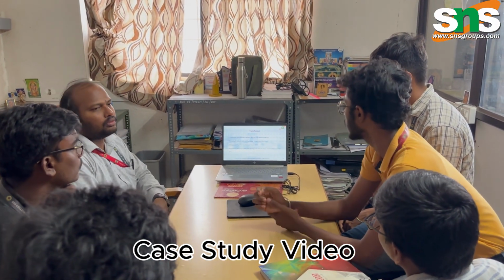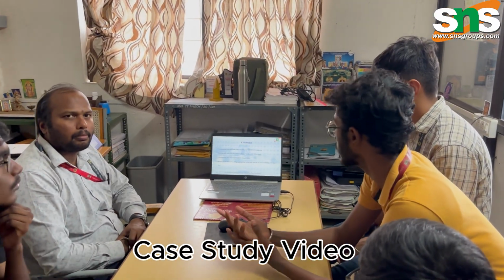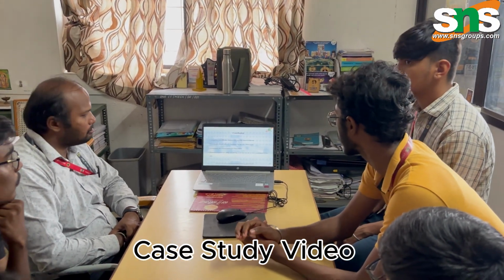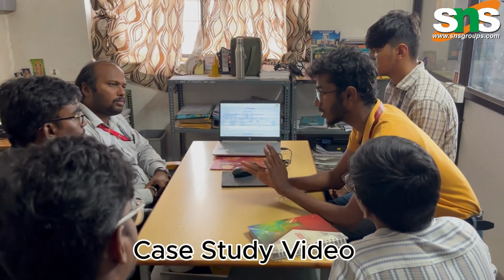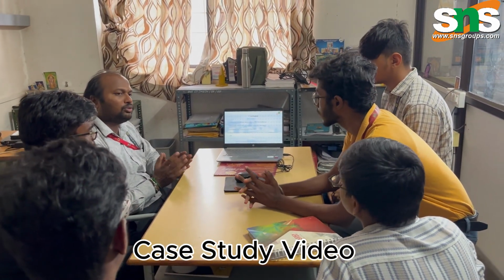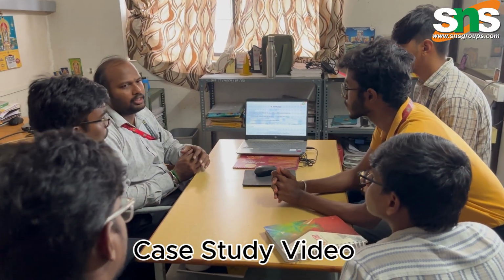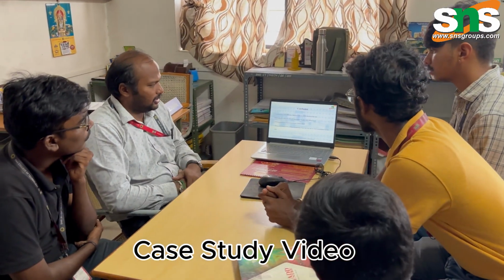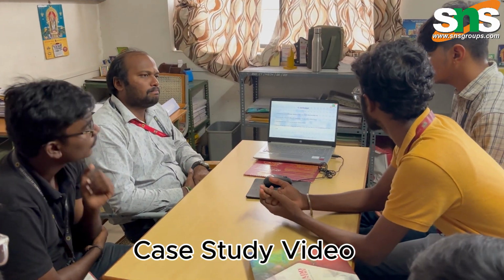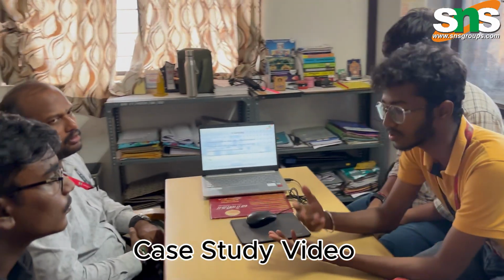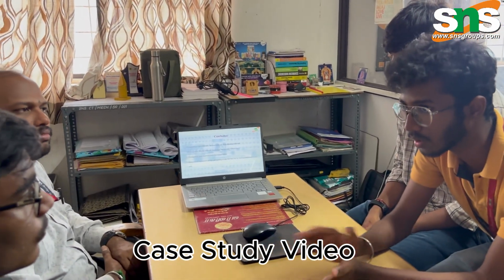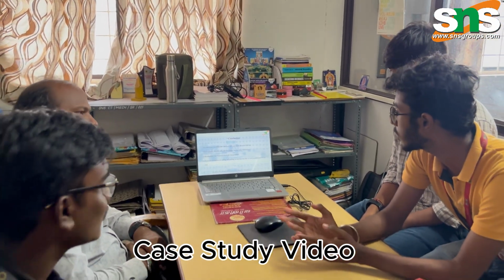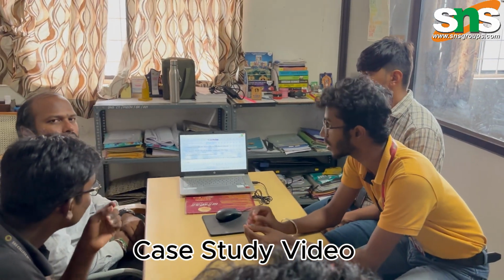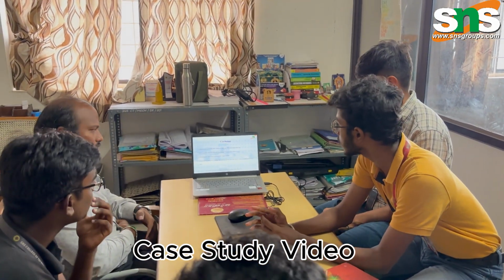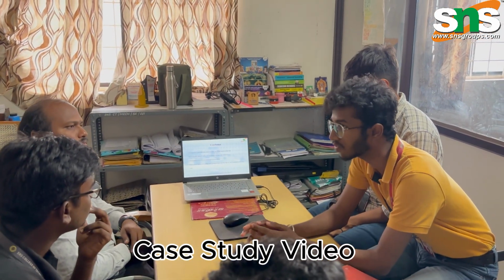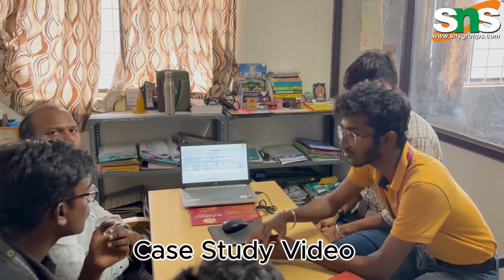Now coming to the conclusion. The composition, the microstructure and the hardness of the gear are satisfactory and at the normal level. The pre-processes, meaning the heat treatment and other machining processes, were normal and satisfactory. Then the fractographic features included the fatigue striations, the fatigue marks. That is the major cause for the failure of the gear. There may also be some misalignments that can cause the failure. The formation of destructive pitting and spalling, which we have seen in that image, is also one of the causes of the failure.